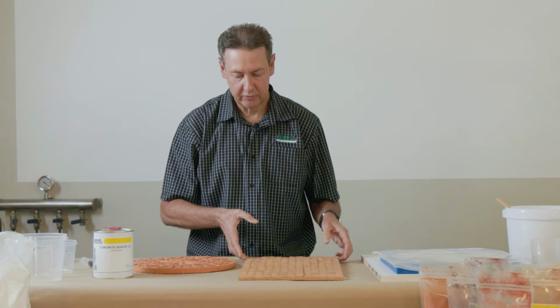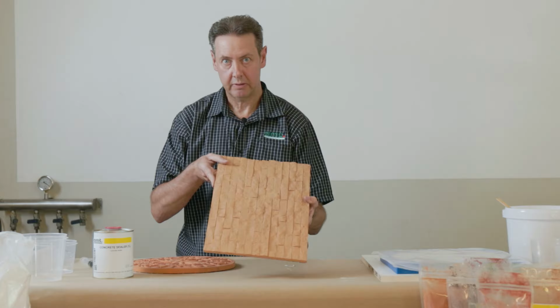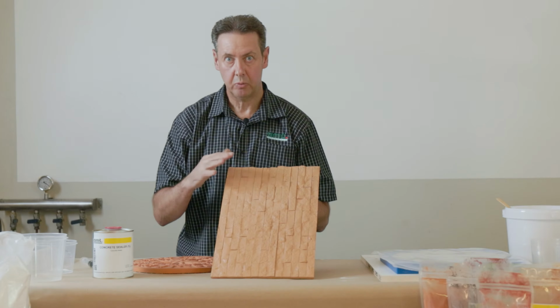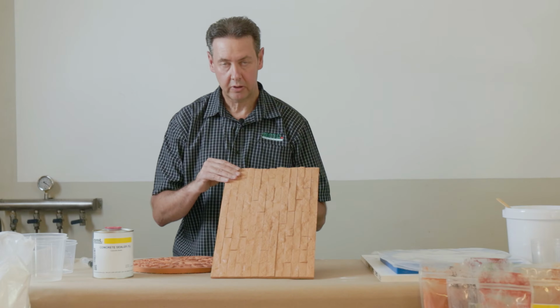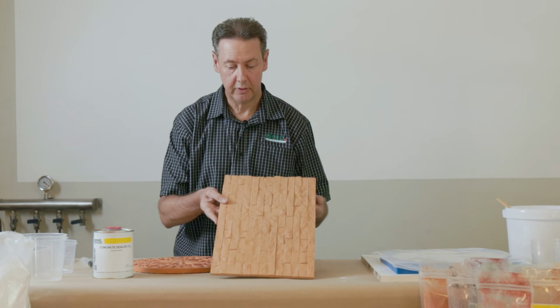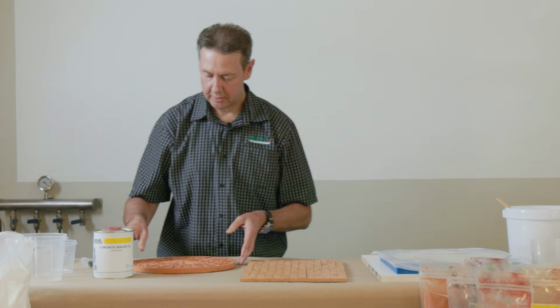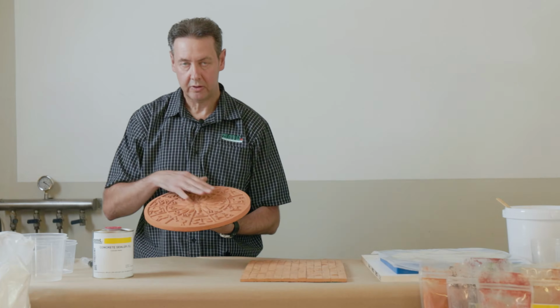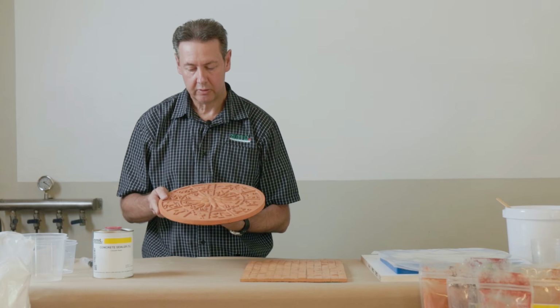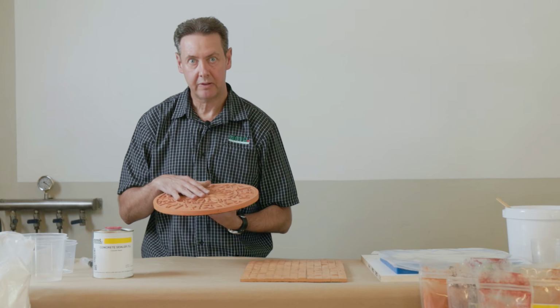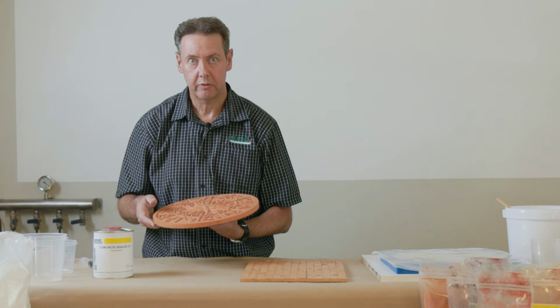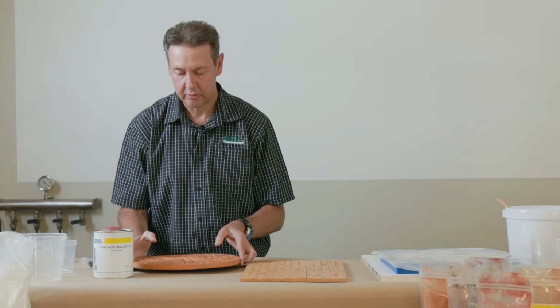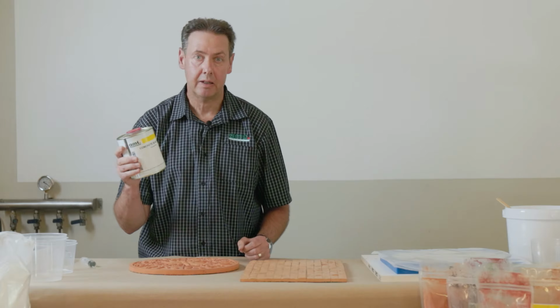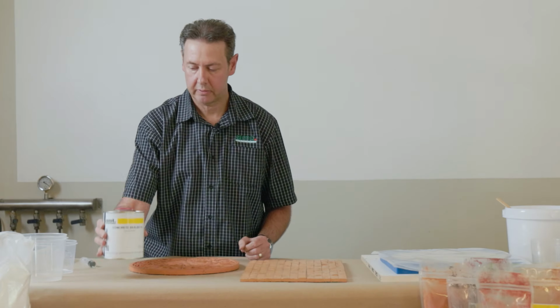So this is a piece that has been actually sealed with the concrete sealer. You might pick up a little bit of a gloss finish on that. This is just basically one coat of the concrete sealer. You can put 2 coats on or 3 coats. It's going to build up that glossiness a little bit if you do that. And then we also have this piece which hasn't been sealed, and you can see a little bit more of a matte finish. But definitely the concrete sealer will keep parts sealed up nicely. And if you're washing them or cleaning them later, it's going to wash off much, much easier. This concrete sealer is a water clear color, and it's also very good in terms of being UV stable and staying clear as well, and not yellowing. So that's the concrete sealer. We've got this available in 1 liters, 5 liters, and 20 liters.